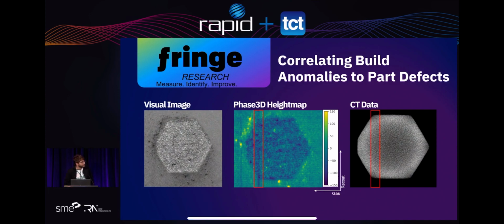Basically, a streak is going through the part, which is creating an anomaly in the powder layer. And amazingly, we saw a streak of porosity in the CT scan data that correlates to the same height where the recoater blade dragged something over the part. So this kind of data is what was used in the study to establish that a threshold of 42 to 47 micron anomalies significantly impacts porosity formation in these metal parts.